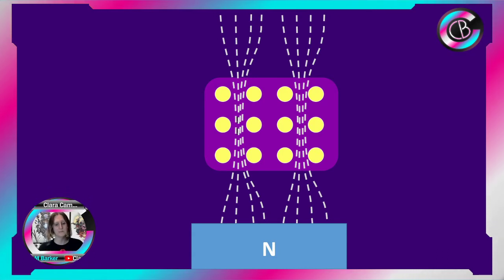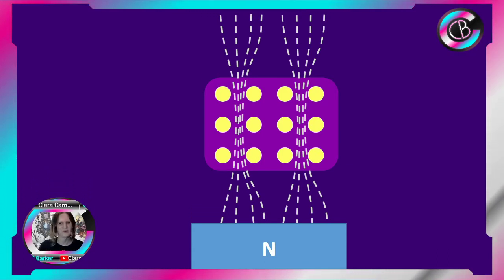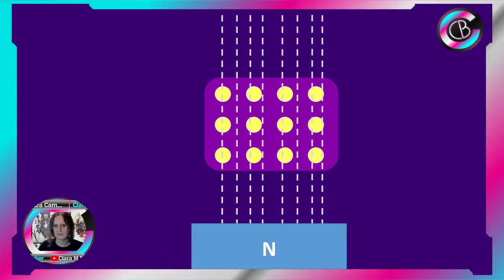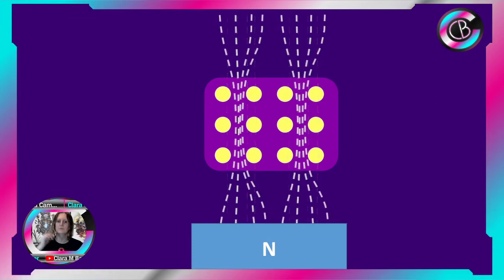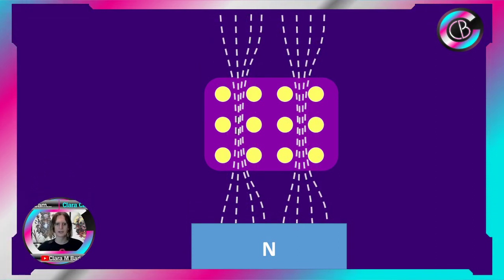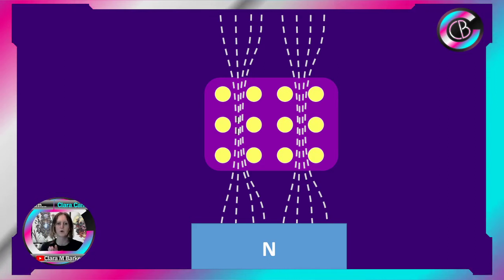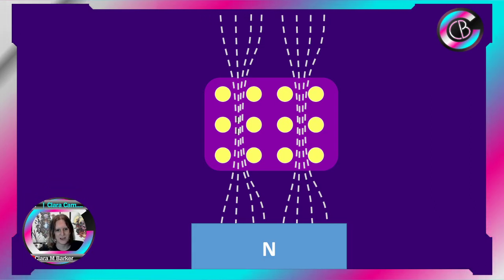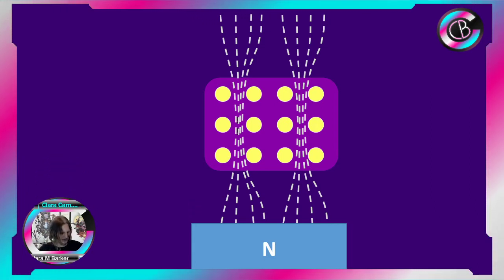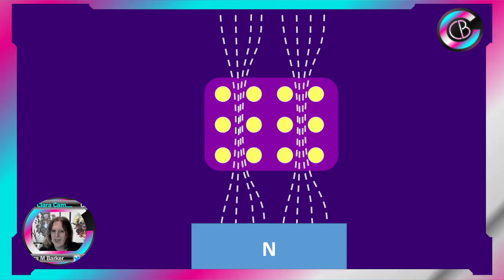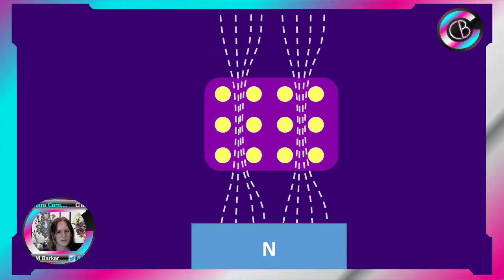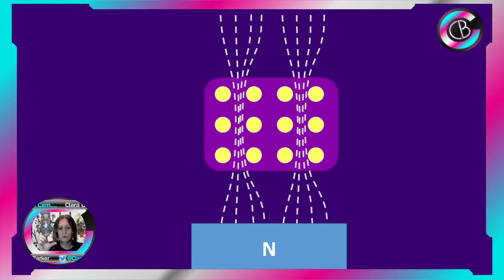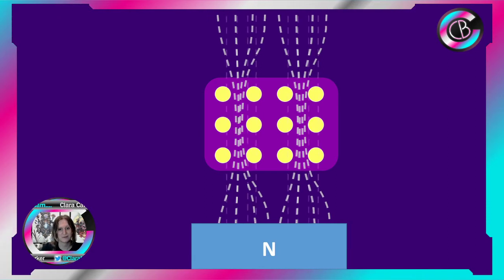But if you cool it down in the presence of a magnet, which is what I sort of did here, as we're cooling it down in the presence of a magnet, and all of a sudden we hit the critical temperature, we've trapped the magnetic field, and it's being forced through these particular points. This is how we trap magnetic fields. It's called flux pinning. And what's really cool is that if you then, having cooled it down, keep it cold and move the magnet, the superconductor and the magnet want to stay in the same relative position.